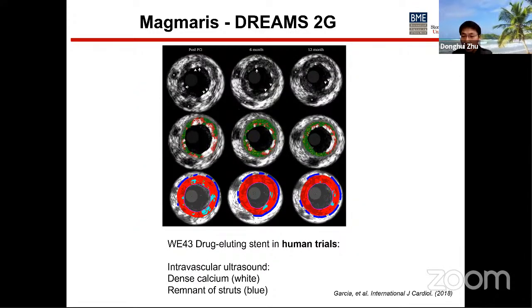This is also from human trials, the intravascular ultrasound data. The DREAMS 2G showed a continuous, favorable safety profile and stable performance up to 12 months in human trials. Following implantation, restoration of vessel geometry, vessel motion, and bioresorption were observed up to 12 months, and the lumen size was largely preserved. So the outcome is pretty good.